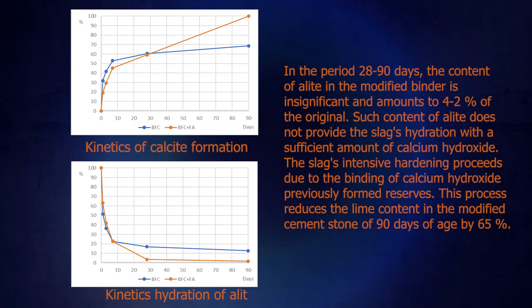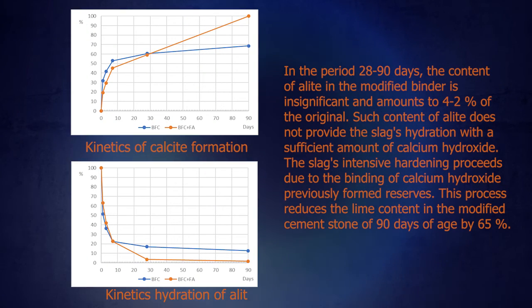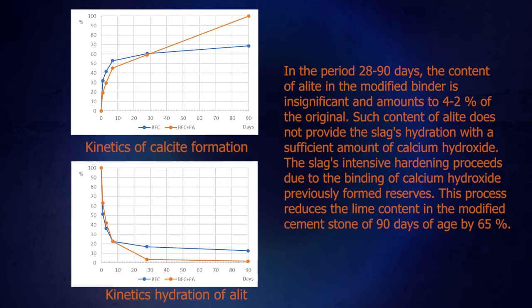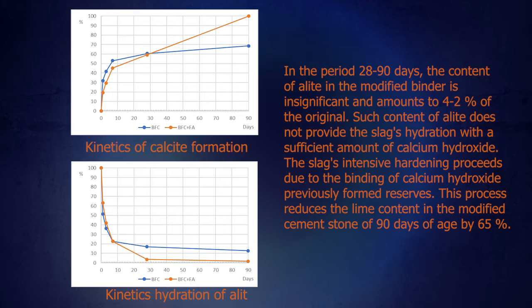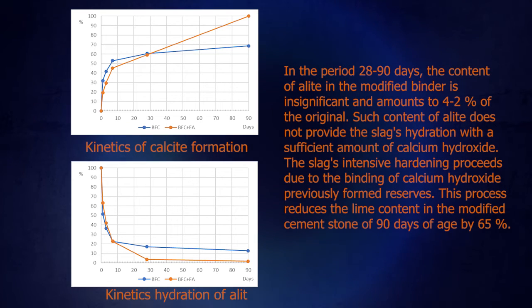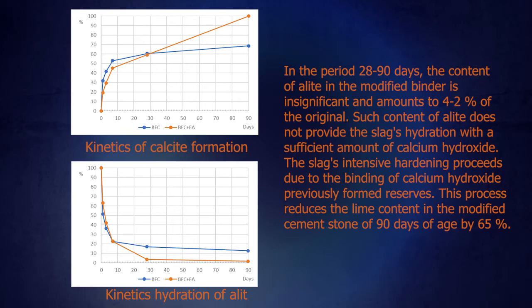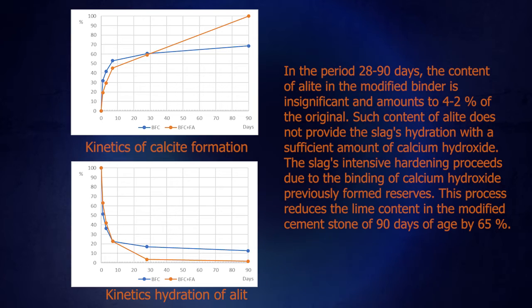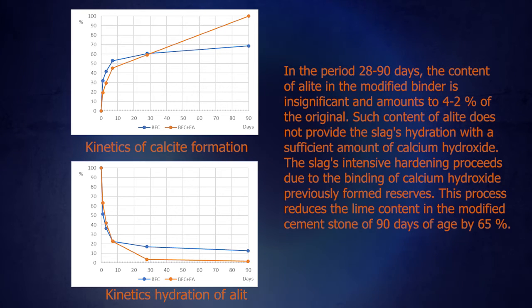In the period 28-90 days, the content of alite in the modified binder is insignificant and amounts to 4-2% of the original. Such content of alite doesn't provide the slag's hydration with a sufficient amount of calcium hydroxide. The slag's intensive hardening process occurs due to the binding of previously formed calcium hydroxide. The process reduces the lime content in the modified cement stone of 90 days of age by 65%.